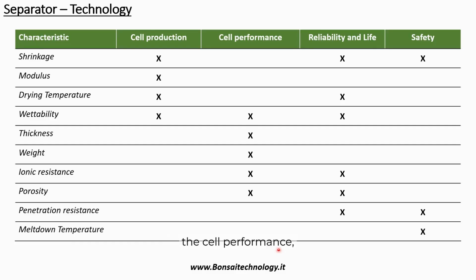The ionic resistance affects the cell performance because the ionic resistance of the cell, so the resistance at lithium ion flow, affect the performance, because with high ionic resistance, the ion cannot pass through the separator very easily and very quick. So we cannot have a power battery cell, but maybe in this case we talk about energy battery cell. And the very high ionic resistance can even increase the temperature inside the battery cell during the working life. And again, the porosity, for the same reason, is very correlated to the ionic resistance sometimes, and we spoke about it before. And then we have the penetration resistance and meltdown resistance that are two important KPIs for the safety, for the reason that I mentioned before.